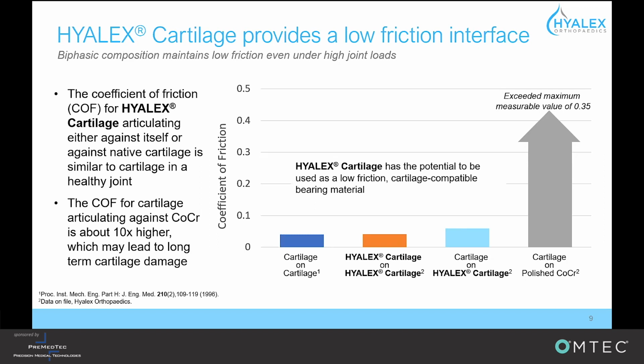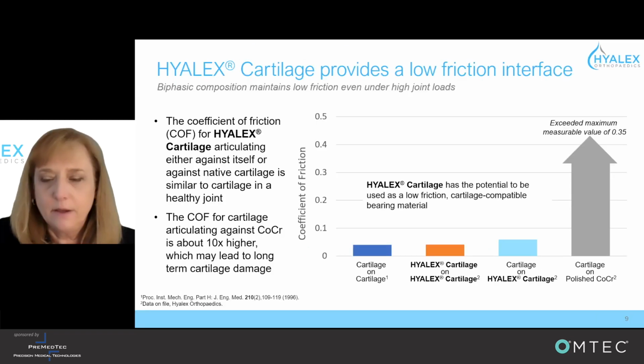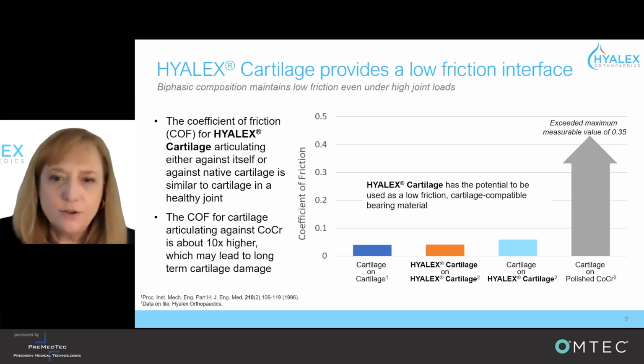Because its design mimics cartilage, Hylex cartilage has an extremely low coefficient of friction, similar to the cartilage in a normal healthy joint. Coefficient of friction measurements of various combinations of cartilage and Hylex cartilage are shown in the figure on this slide. Both Hylex cartilage articulating against itself in the orange bar and Hylex cartilage articulating against normal cartilage, the light blue bar, have very low friction coefficients, similar to cartilage in healthy joints. In contrast, cartilage tested against a polished cobalt chrome surface has a coefficient of friction that's about 10 times higher.